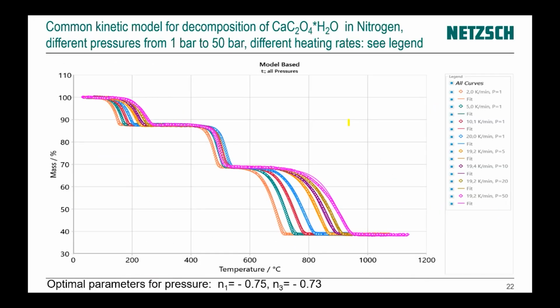That was this example. What is interesting is that the parameter of the pressure is -0.75 for the first step, and the dependence on the pressure is 0.7 for the second step, minus 0.7. According to the theory, the diffusion coefficient has a dependence on the pressure with the degree -1. But here for the solid reactions, we see that the order of reaction, or order of pressure in this case, is not equal to 1, which is typical for solid reactions.